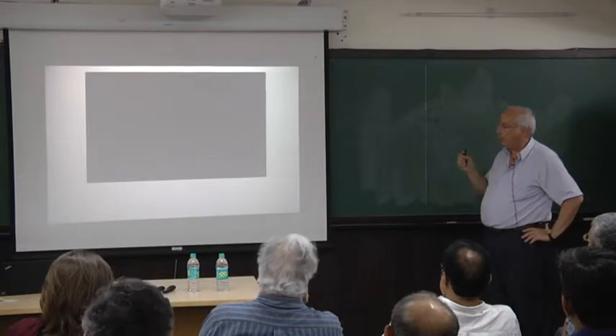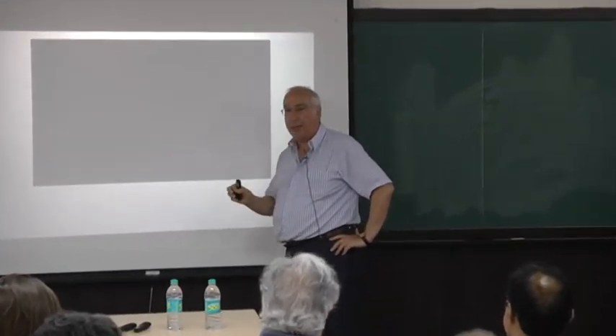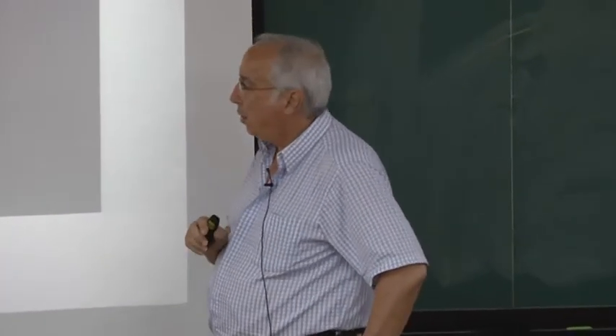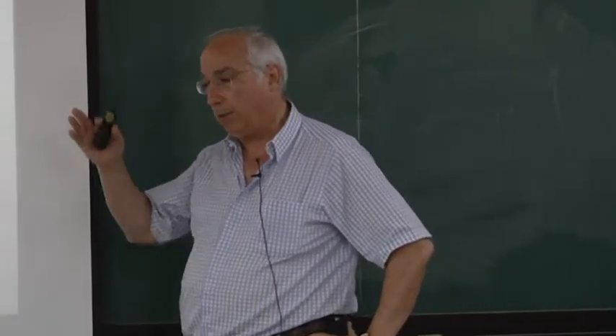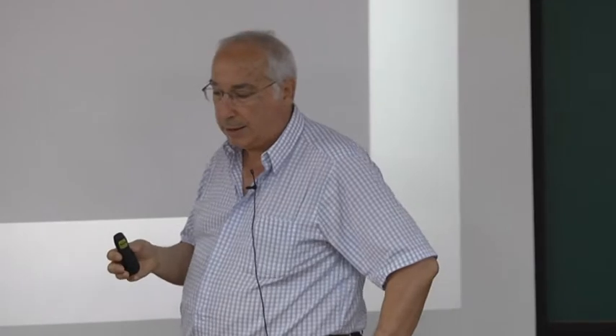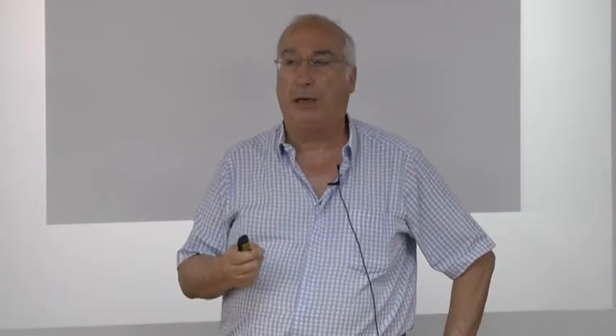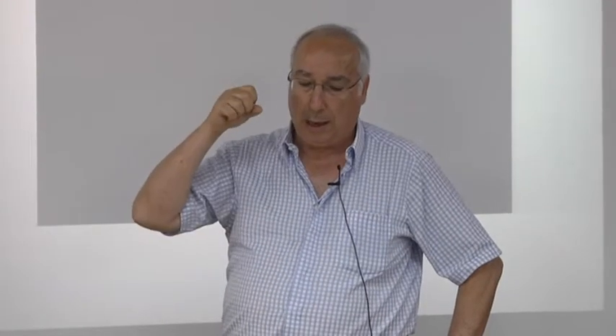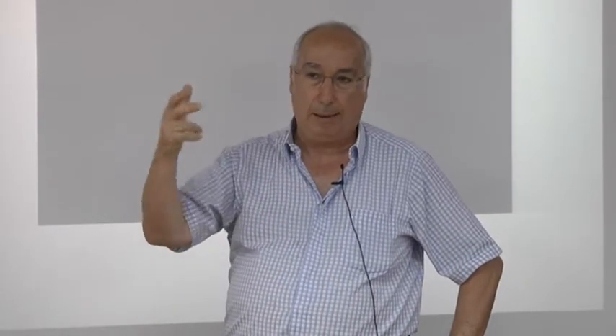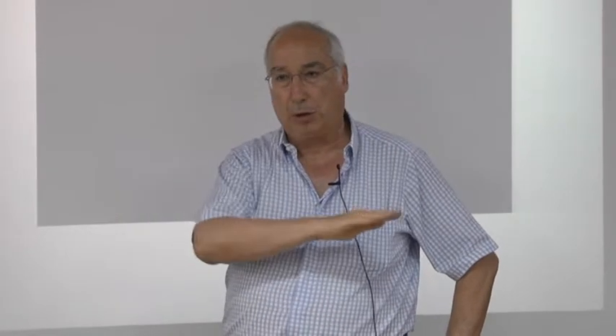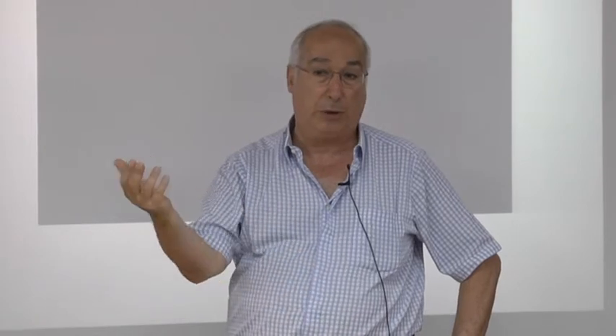What I want to show you now is a very nice experiment that introduces the notion of a metallic glass. Now, as I said, in general, metals prefer to crystallize. So in order to make a metallic glass, which people have already known for years, you either quench it very rapidly. In the 1960s already, people were making metallic glasses by quenching at a rate of 10 to the 6 Kelvin per second. And the best way was to take a molten binary mixture and spray it on a cold substrate, so you get a very fast cooling, but this way you could get only films of metallic glass or ribbons.